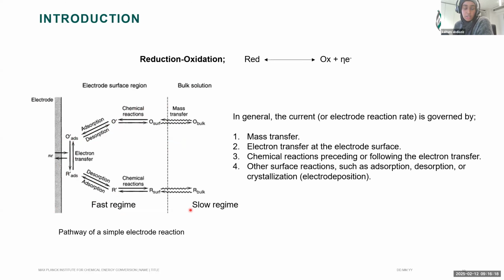In general, the current that you experience in your system is affected by all these different processes: your mass transfer, the electron transfer to and from your electrode, and any chemical reactions that are occurring. In a steady state condition, all of these are kept the same, but you might get some sluggishness from one process or another, and this results in what we call the rate determining step. So with electrochemistry, you can really investigate all of these processes that are going on.